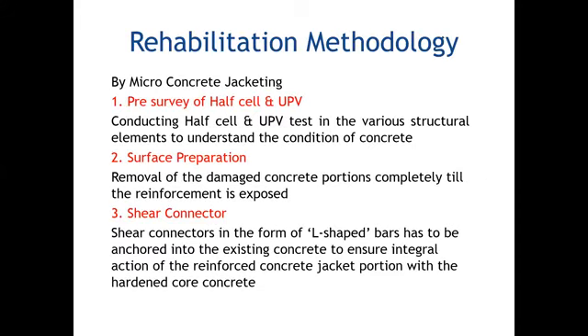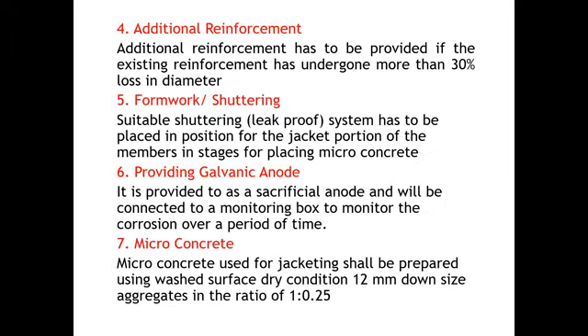Do the pre-survey of half-cell and UPV, do surface preparation, provide shear connectors, additional reinforcement, formwork, and galvanic anodes. Now, as the professor said already, a number of methods are available, but the industry at present is using galvanic methods very handily, because one of the biggest advantages here is that not only is addressing the corrosion easy, but monitoring the corrosion levels is also much easier.